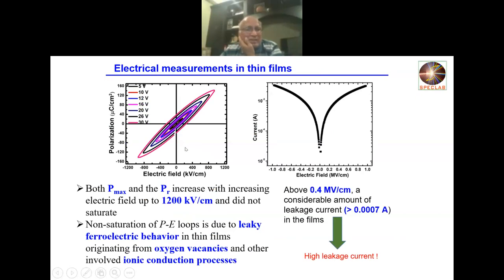Ferroelectric properties, that is the polarization loop, was very leaky in this material, as in the other case. That's mainly because of the oxygen vacancies, and other conduction processes might be there too. And you can see here also the leakage current is very high.